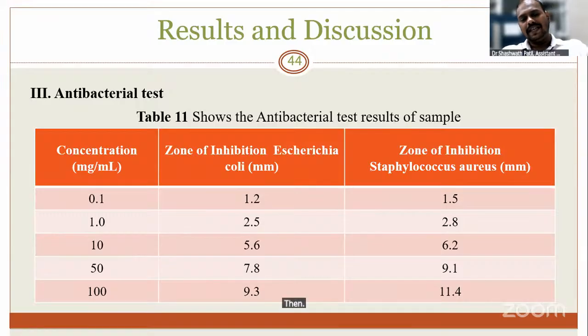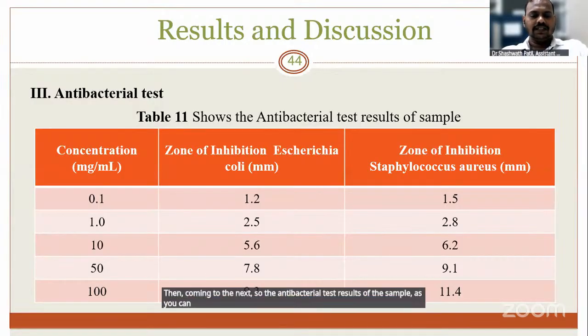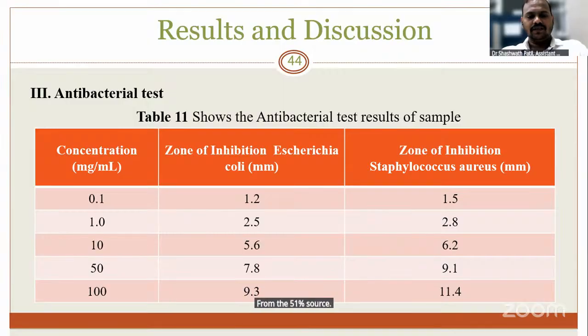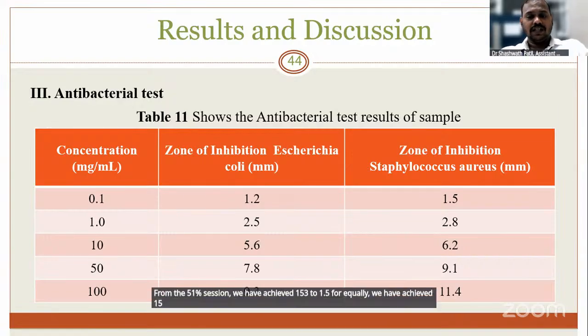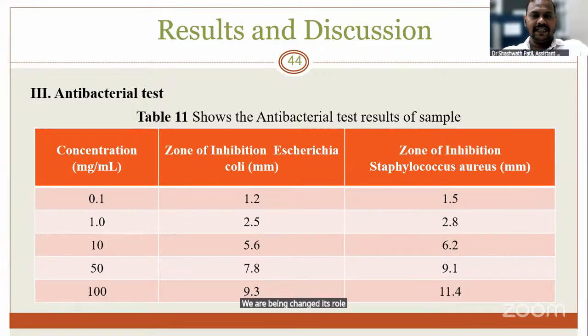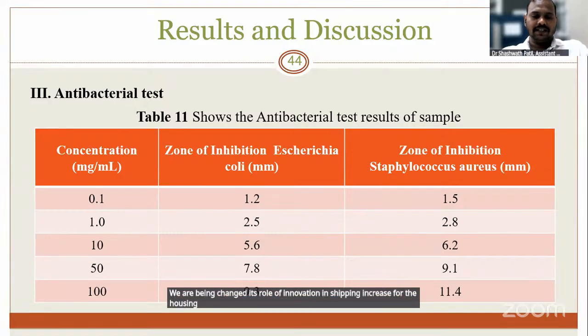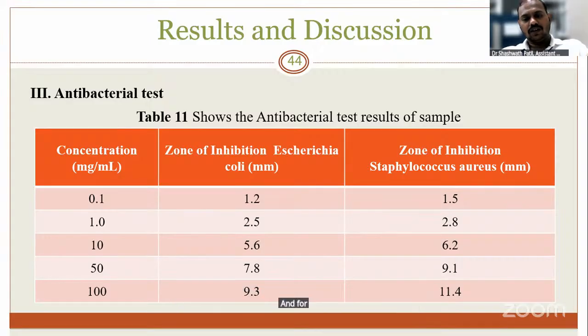Then coming to the next, the antibacterial test results of the sample. As you can see, with the concentration increasing, the zone of inhibition increases. For 0.1 concentration, we have achieved 1.2 to 1.5: for E. coli, 1.2, and for Staphylococcus aureus, 1.5. As we increase the concentration, the zone of inhibition increases. For 100% concentration, we have achieved a maximum of 9.3 for E. coli, and for Staphylococcus aureus, a maximum of 11.